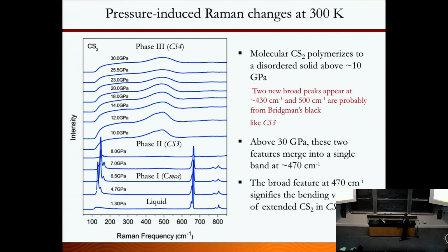While we were doing this, you can see the changes in this Raman spectrum and the intensity. What you're seeing is vibrational spectroscopy: lattice modes, the stretching vibration, and the overtones. Around some pressure, everything disappears and you get a new broad peak, and two broad peaks merge into one new peak. This also indicates a new phase transition right here.